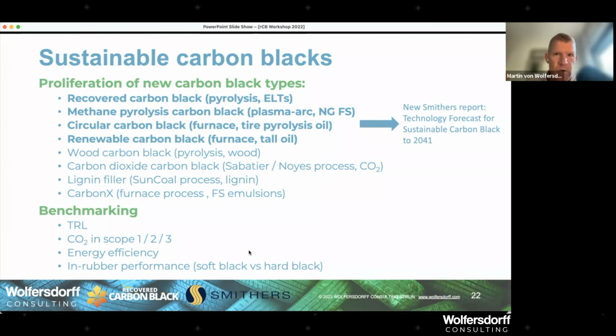This is the benchmark. This is the theory. And of course, every real process needs more energy. Some processes more than others. And this is what I'm suggesting as the benchmark, because the pyrolysis is the key, the core or the heart of the plant. Clearly, milling is also eating energy. Drying is using a lot of energy because we have to evaporate the water, which is very energy intense. So I think at one point we need to combine all the energy use of the whole plant per ton of recovered carbon black. But to start with, I'm suggesting just to look at the pyrolysis and the efficiency of the energy use in the pyrolysis. Hope that has answered your question, Ali.